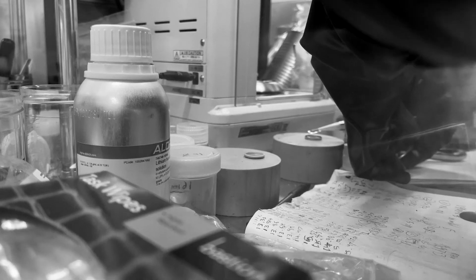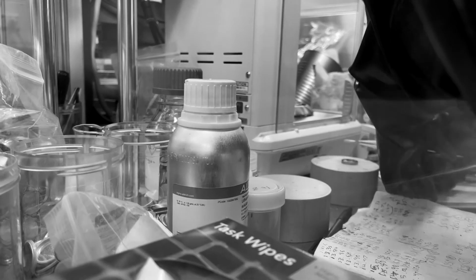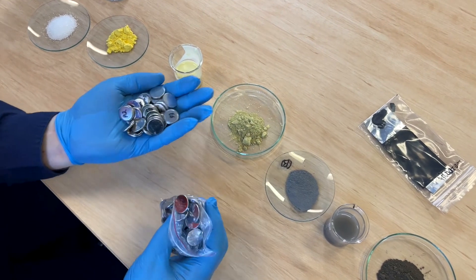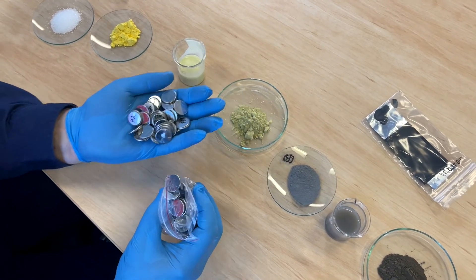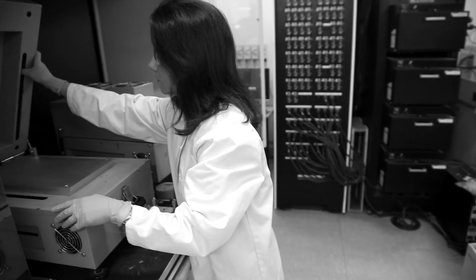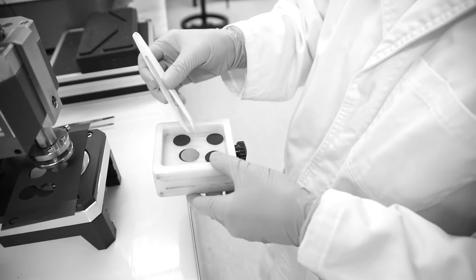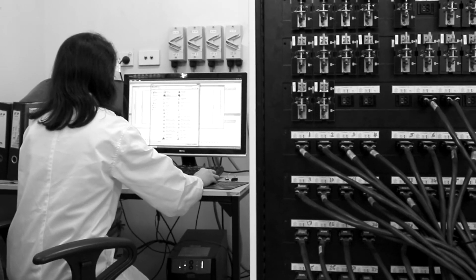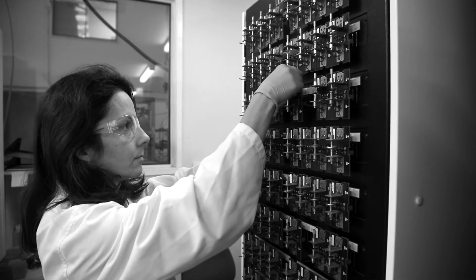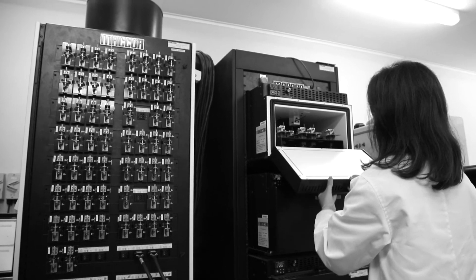The way we test this final product is we actually make batteries out of it. The best way to test a product is to understand how it performs in a battery. So we coat the LFP powder onto aluminium foil, that foil gets included into a battery like this, and we put it on a specialized testing machine that cycles it — puts it through its paces — and from that we understand what sort of specific capacity the powder has, what sort of rate performance we can expect, and also the cycle life.